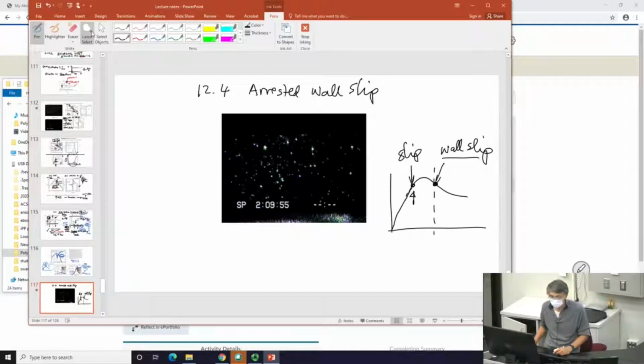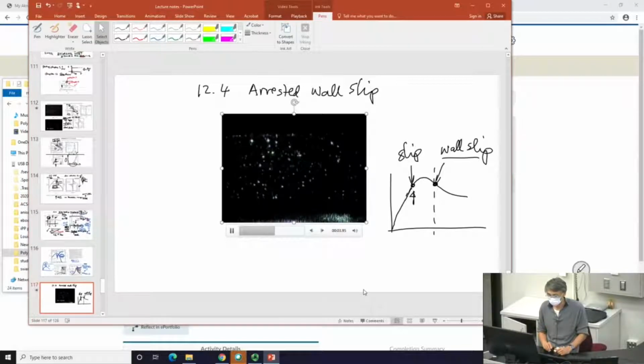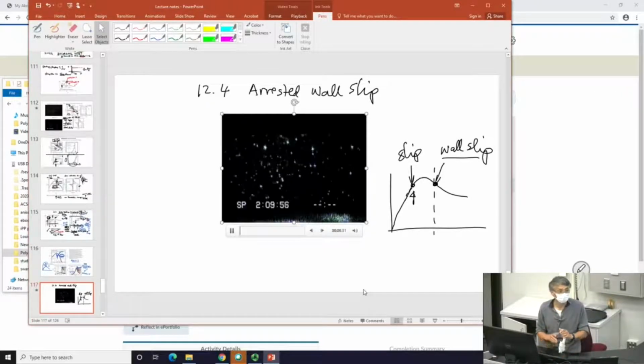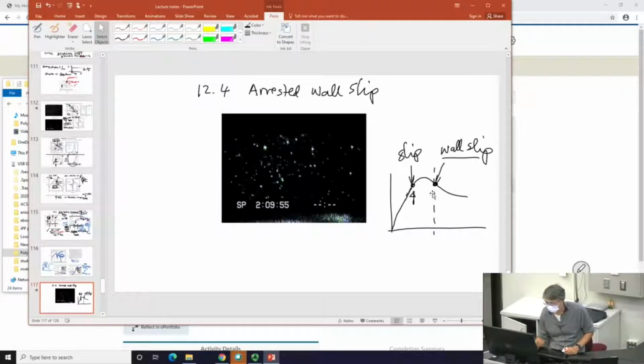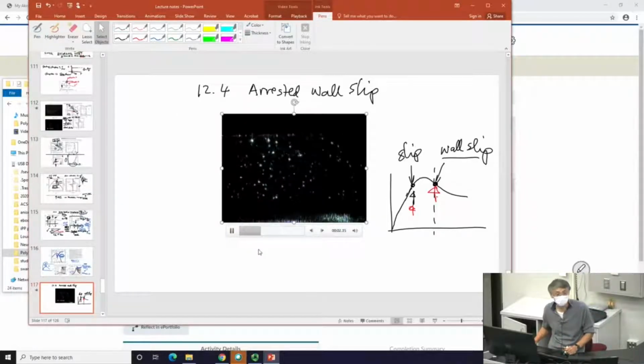So this is surely very strange. How can you? So here is the case, though. The movie was taken after we made the prediction. Puyang was patient enough to make this experiment work. You have to make sure your surface is so clean. You have to have perfect adsorption of your polymers so that you could delay your slip in a startup shear to this point. But he wants to demonstrate this can occur earlier if you stop. And this movie just shows it does. In other words, by the time he stopped the shear, no slip occurs yet. It occurs after you stop the shearing.